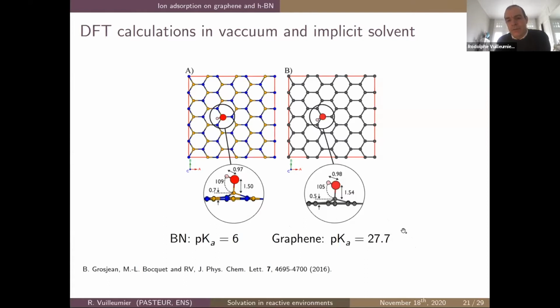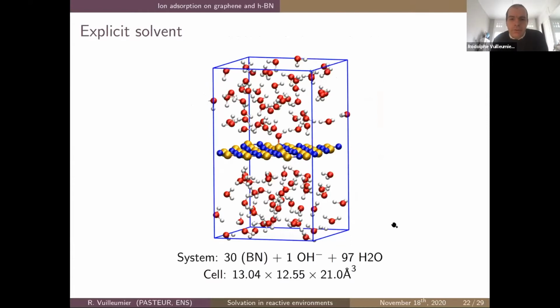Experimentally, we would like to have a pKa for graphene of around 9 or 10, and this is much too large with respect to the experiments that were conducted by Lydéric Bocquet. So what is missing is probably the solvent. Perfect. Thank you, Marco. So we introduced the solvent explicitly using, again, first principles MD simulation, here for BN, but we did it also for graphene with an extra hydroxide in the cell.